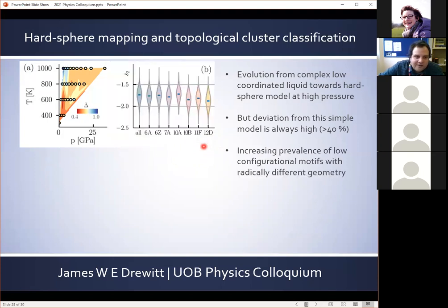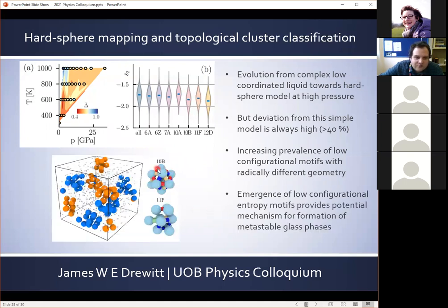And interestingly, we find that these five-fold symmetric 10B and crystalline 11F units, as you recall, which increased in their prevalence close to the melting curve at high pressure, are also the units with the lowest configurational entropy, as shown here on these violin plots. And we postulate that the competition between these radically different forms of emergent structural units, but with low configurational entropy, may help to stabilize a metastable metallic glass in the high pressure supercooled liquid. Although this is highly speculative, it could be a route to forming novel metallic glass materials at high pressure.